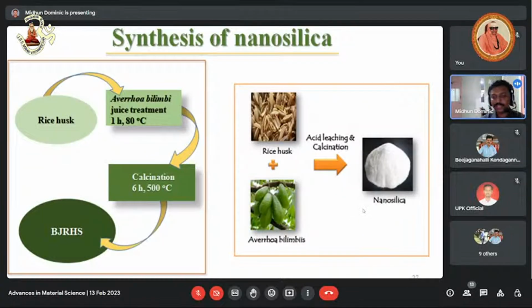We thought the lower surface area of rice husk ash may be one of the reasons for its detrimental effect, so we would like to improve its surface area. How can we improve the surface area of rice husk ash? We thought it is better to prepare nanosilica. There are several methods reported in the literature for preparing nanosilica, like the sol-gel method, where we can make use of TEOS, or the precipitation method using sulfuric acid in sodium silicate solution.